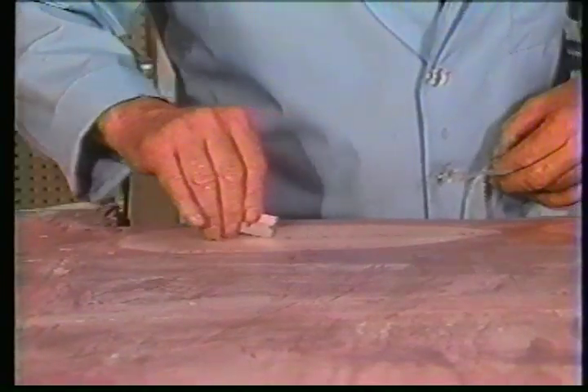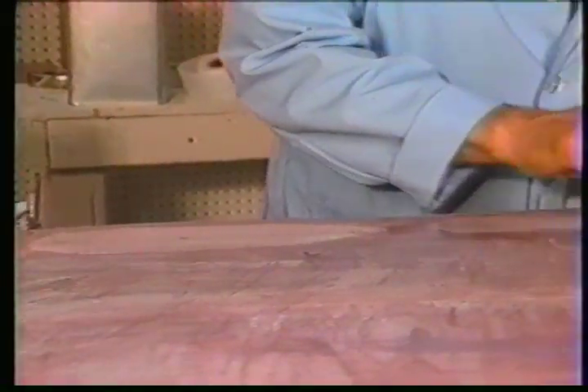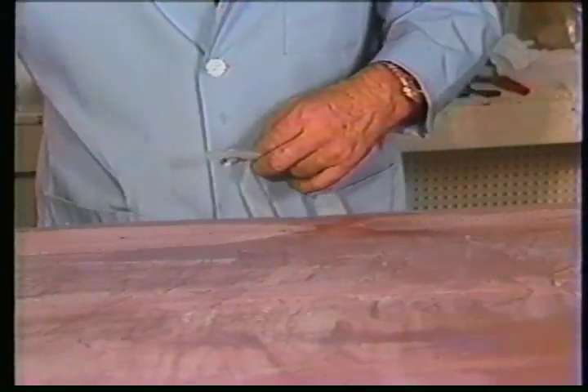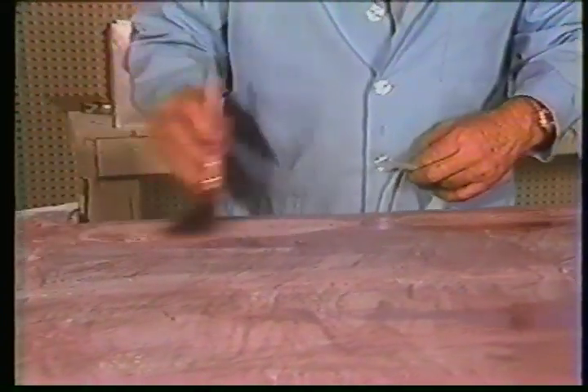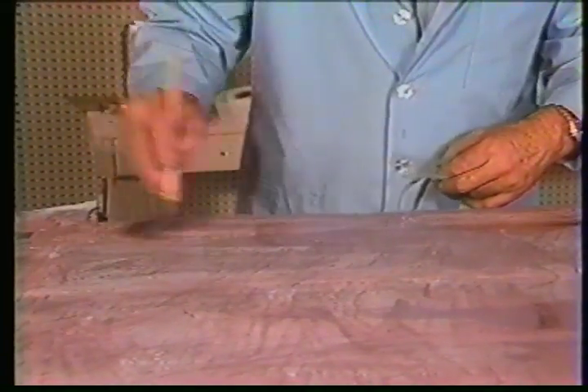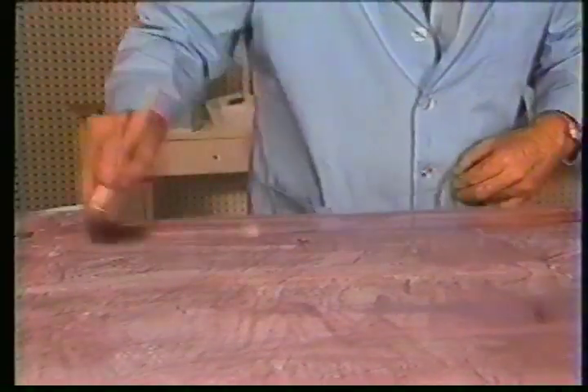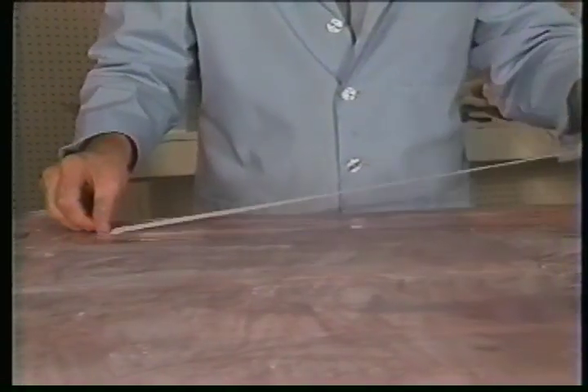If a plywood surface has a deep warp and the fabric will not stay down, the most practical fix at that late stage is to coat all the surrounding area to stabilize the fabric. Then, carefully cut the fabric across the center of the void and cover the slit with a finishing tape.